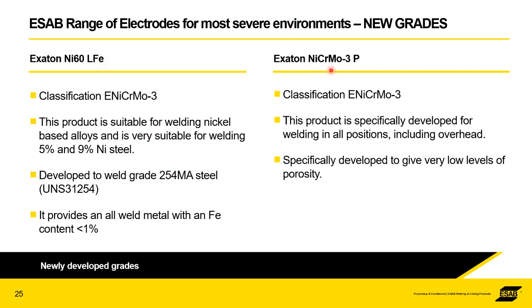And the second one, again, is another derivative of the 625, a nickel chrome moly 3. This is nickel chrome moly 3P, very specifically designed for all position welding. So this gives a much better quality of weld, and it's easier to weld in all positions, including overhead. Whereas some of the grades previously suffered from not being very friendly to weld in all positions and maybe giving a little bit too much porosity, this one's been specifically designed for all position, overhead and low porosity welding.